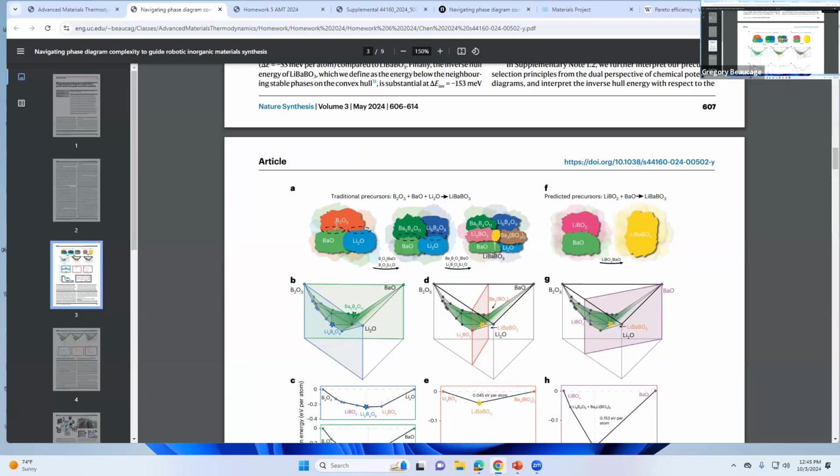And they make the claim that when you mix these, which are crystalline particles of these oxides, there are certain reaction pathways that are favored, and there are going to be binary reactions. In other words, the green one will react with the red more rapidly than the green with the blue or the red with the blue. Basically, if you mix 3 of these together, you get certain binary pathways to get to the ternary product that comes out. That's kind of the idea of this.